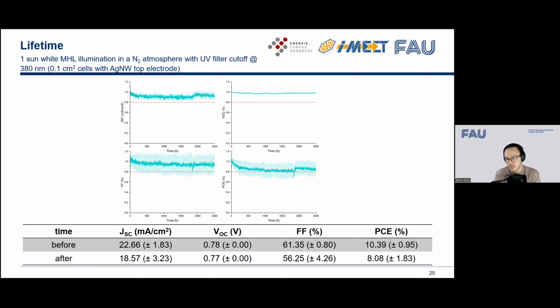And to make sure, because you can see there is an artifact at around 1,800 hours, I wanted to make sure that those measurements are still real. So I took the device out and measured them again with the same setup that was used to measure them initially. And the result of that was quite comparable. So for these specific devices, we didn't reach the T80 time after 2,500 hours with metal halide lamps with a cutoff filter.